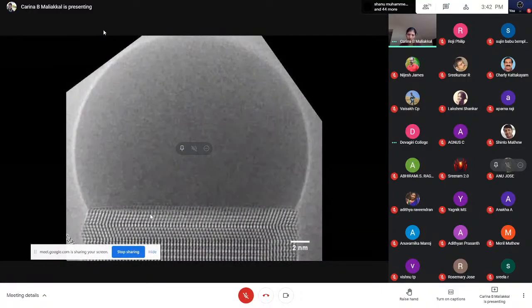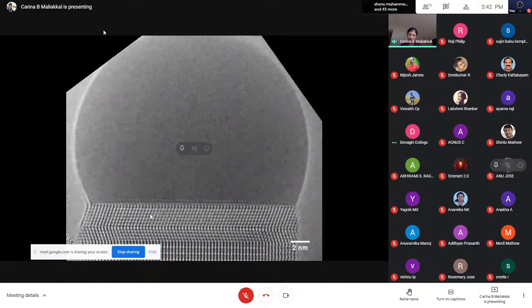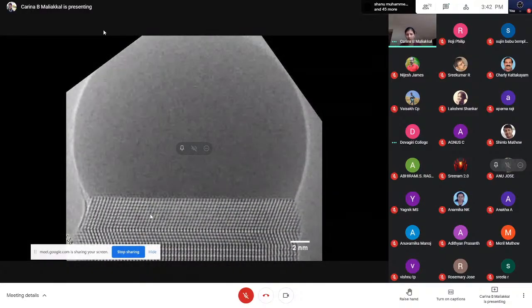So this is an example where you can actually see the two different crystal structures. So you see over here at the bottom of it, it's in one crystal structure, but in between, this region is basically a Zincblende structure. This is a Wurtzite structure. You'll see a little bit better when I show you the video. Yeah. So again, we are seeing that the nanowire is growing, and you are seeing layers growing one after the other.